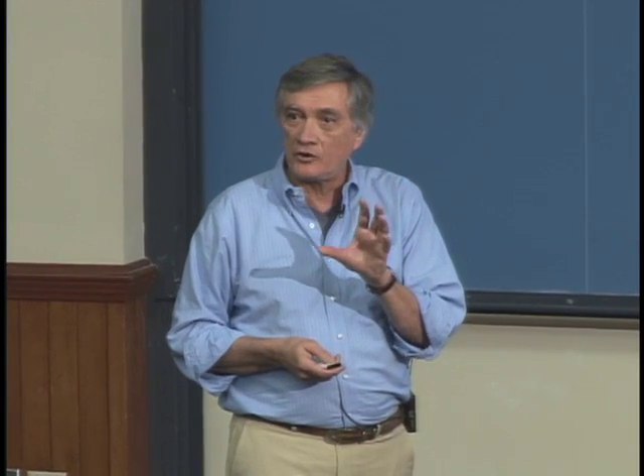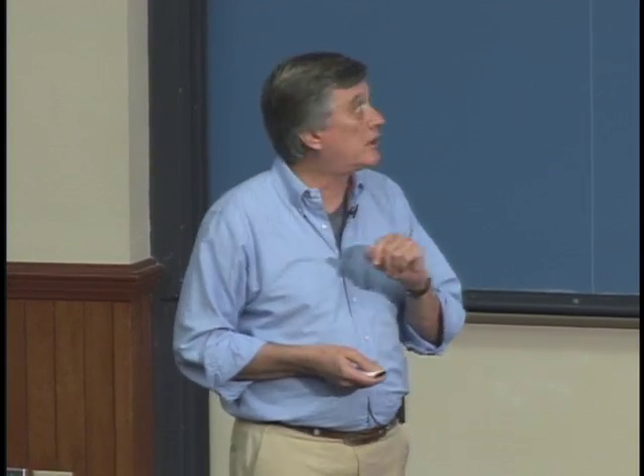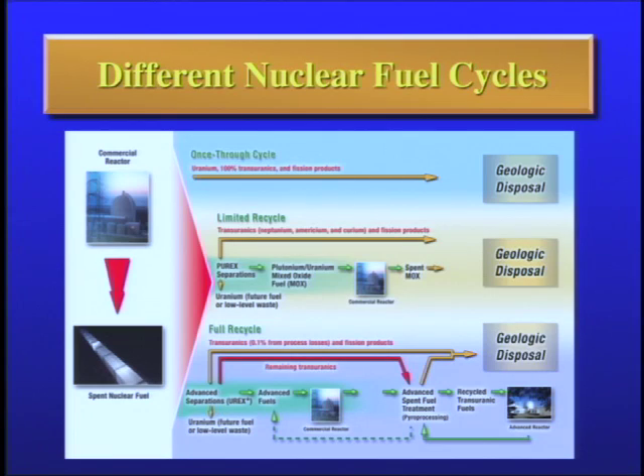Before doing that, though, I want to show you what your choices are in the broadest sense for spent fuel cycles. The top is the once-through cycle. You just burn your fuel in a reactor, give it to a geologist to design a repository. Okay? The arrow indicates as much. A limited recycle would be to chemically process the used fuel, pull the plutonium out, put it into a mixed oxide fuel, back into a light water reactor, and then dispose of the MOX fuel. But as I've told you, you still have the plutonium in your fuel.